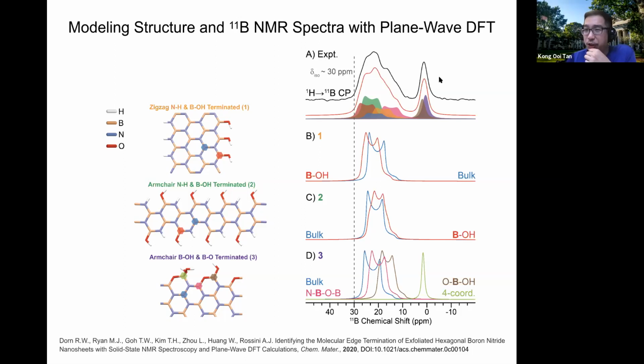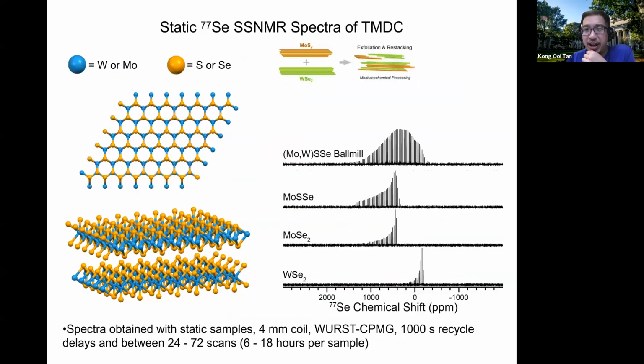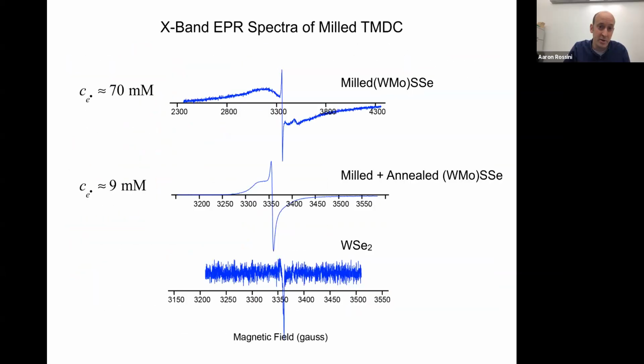I think you show an EPR spectrum where you estimate the radical concentration to be 70 millimolar or 9 millimolar. 70, yeah. Wow, these are actually quite concentrated. This is not the best figure because the scale is changing when you compare these different ones. When you initially mill it, you have this extremely broad signal, which I'm assuming must be g anisotropy due to the selenium or molybdenum or tungsten. And then when you anneal it, that broad background signal goes away and you're left with just that sharp signal in the middle. And that's what we see. But even this one still has a pretty big g anisotropy.